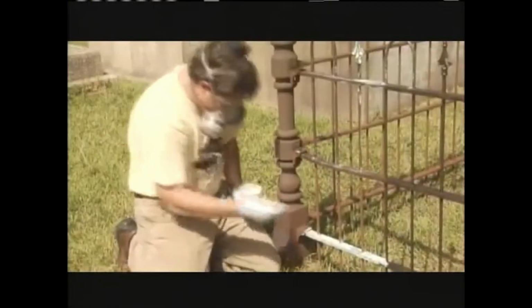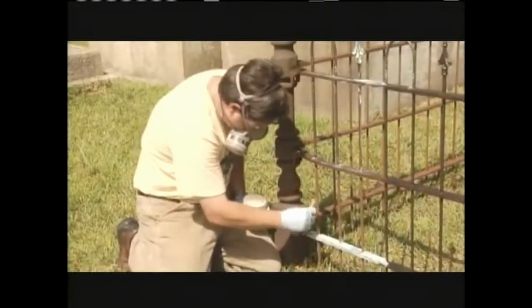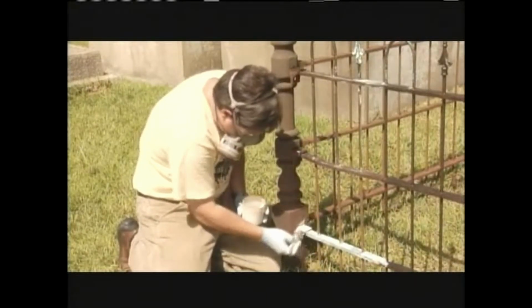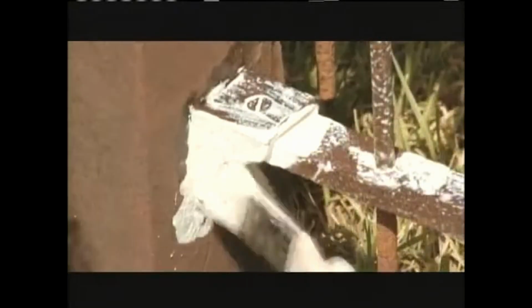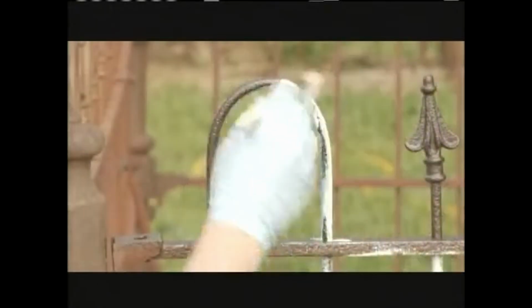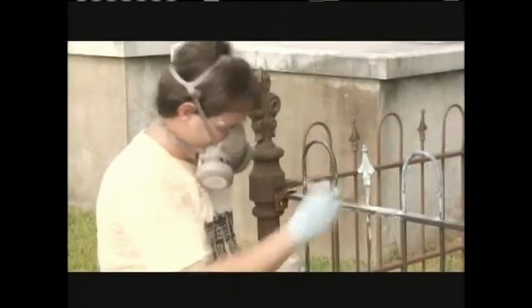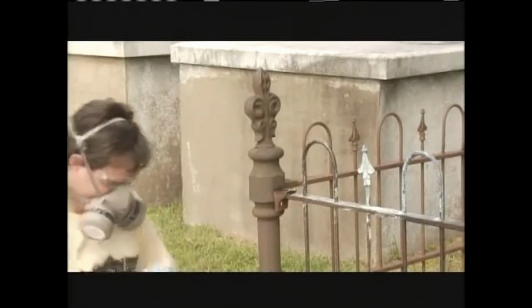The rust converter must be brushed or sprayed on all surfaces of the iron, paying attention to coat any undersurfaces and crevices. Use extreme caution if spraying the converter, because any contact with stone will cause an irreversible black staining. Once all iron surfaces have been treated with the rust converter, it must have adequate time to cure before you can move forward with the restoration. Check the manufacturer's label for the curing time of the converter that you are using.